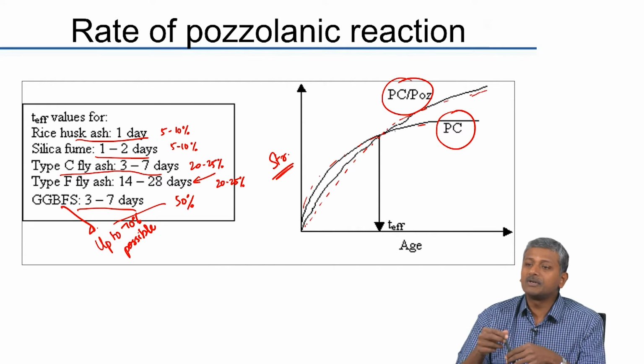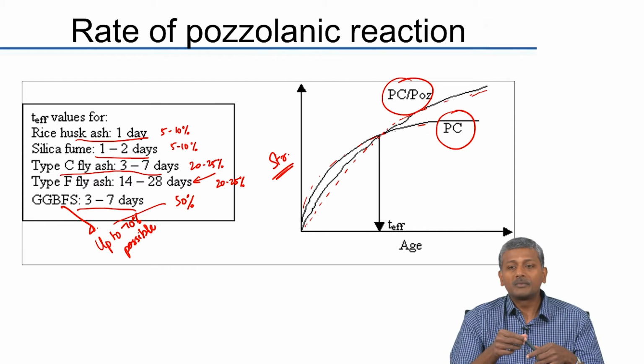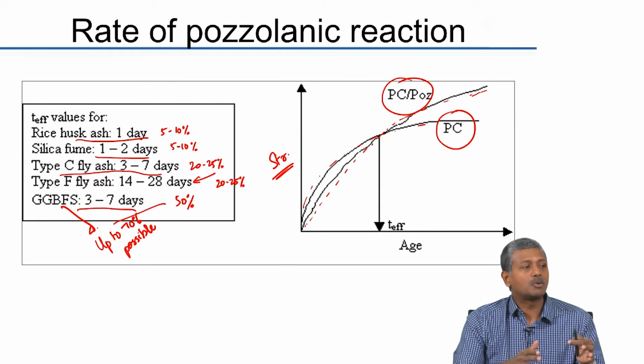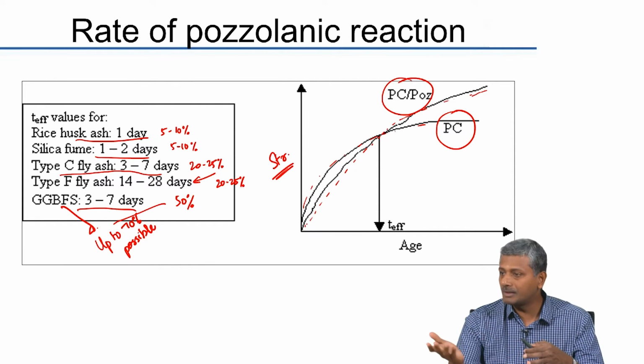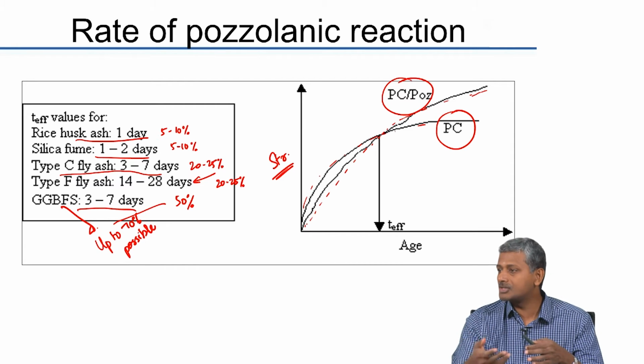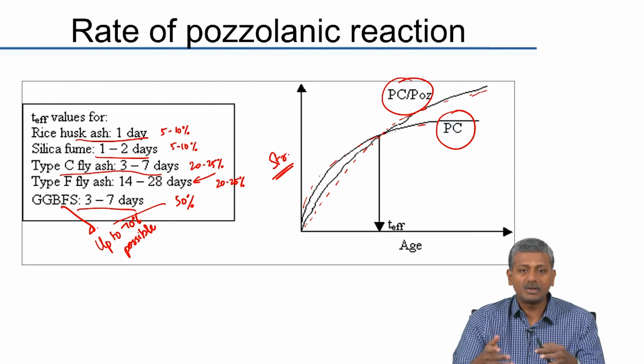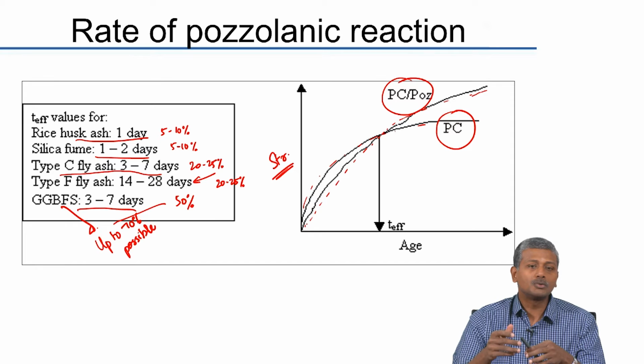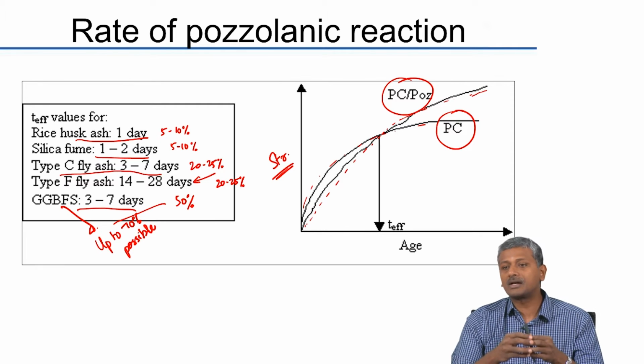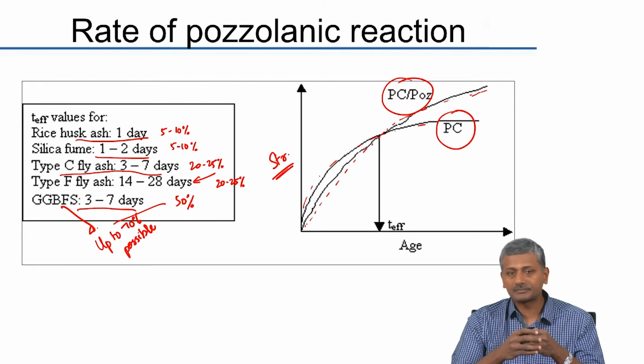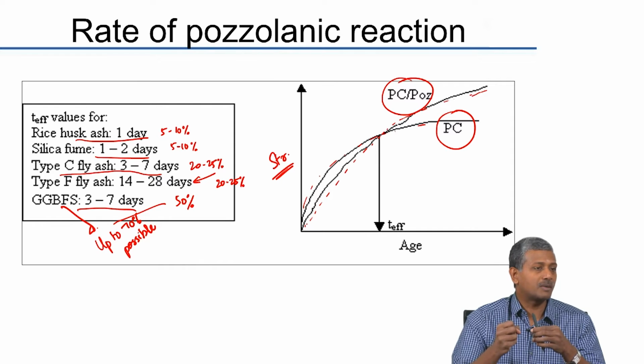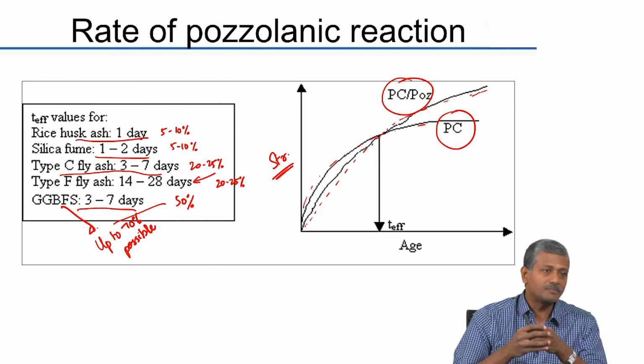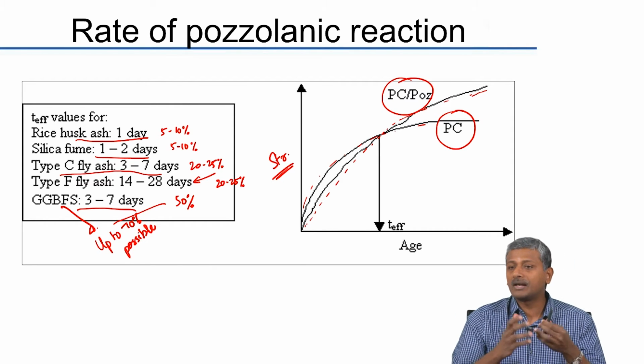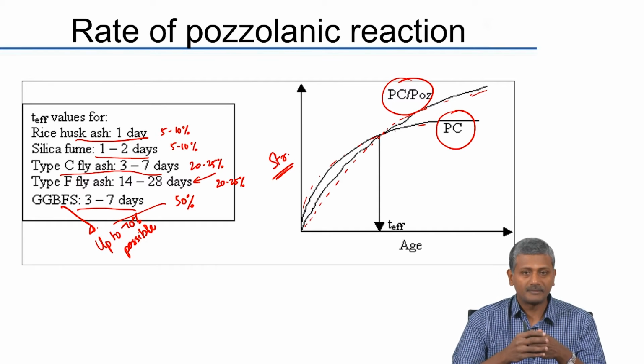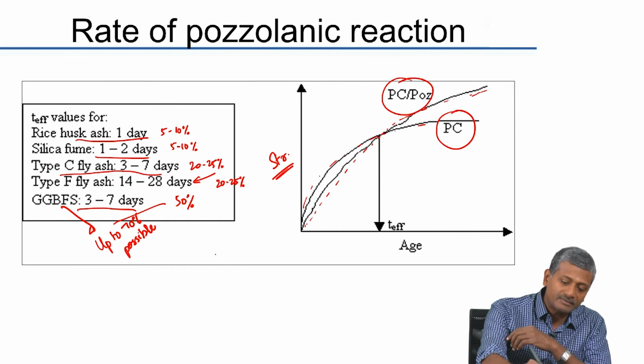So, because of this, what cement companies started doing some time back, because they had a mandate only to sell Portland pozzolan cement for the regular trade segment, that is the residential market and so on, they had to sell only PPC. So, in order to satisfy the customers' demands, they started grinding the PPC very fine. So, when you grind PPC fine, what happens? The rate of reactivity goes up, and they were actually able to grind it to such a fineness that the PPC was giving them a strength which was equivalent to 53 grade cement. In fact, they started marking their bags as PPC 53.